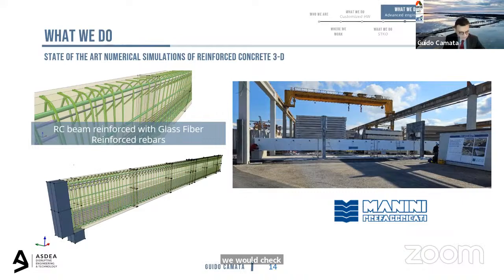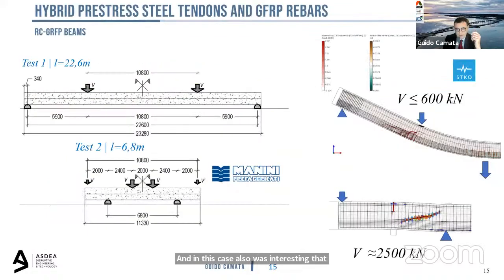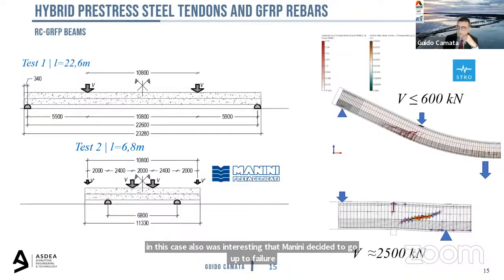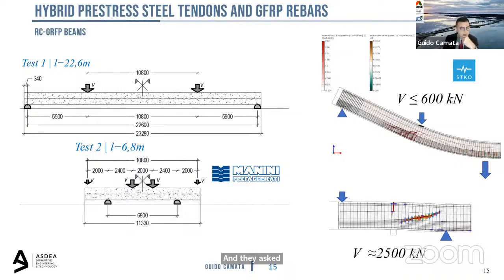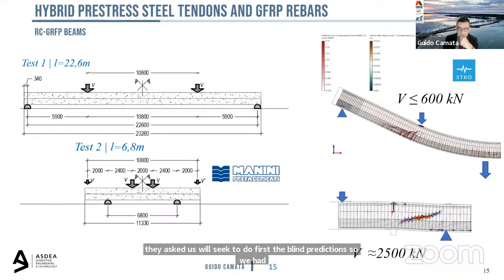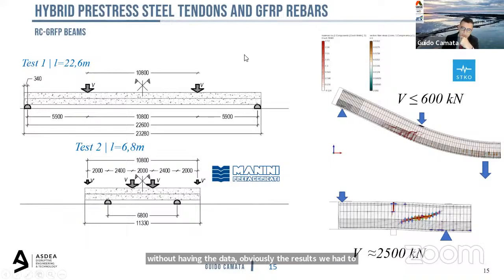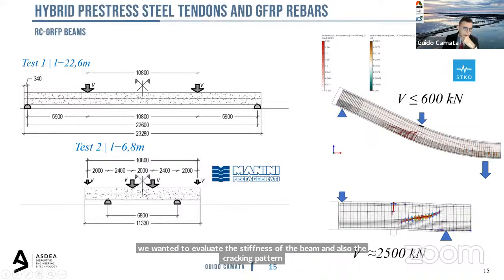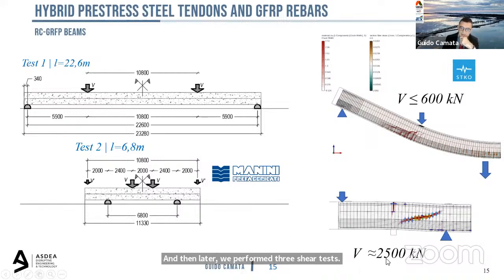And in this case, also was interesting that Manini decided to go up to failure. And they asked us, we will see, to do first the blind predictions. So we had, without having the data, obviously the results, we had to predict the strength. We first performed a 4-point bending test of flexure, and we wanted to evaluate the stiffness of the beam and also the cracking pattern. And then later we performed 3 shear tests. I'm going to show one, and we evaluated the shear strength to 2,500 kilonewton.